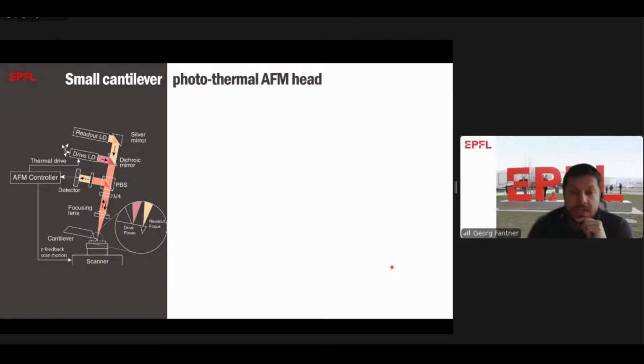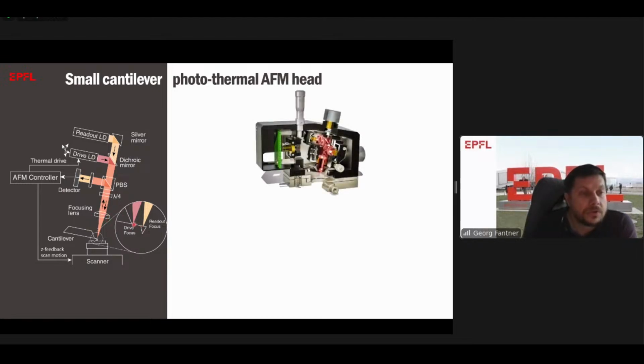Now, of course, we also need a way to drive this laser. And so we've built a modification to our AFMs, where in addition to the readout laser, which you have in most AFMs, we've now added an additional laser, which is also focused through the same objective lens, but now on the base of the cantilever. And here's a cross-sectional drawing of the setup.